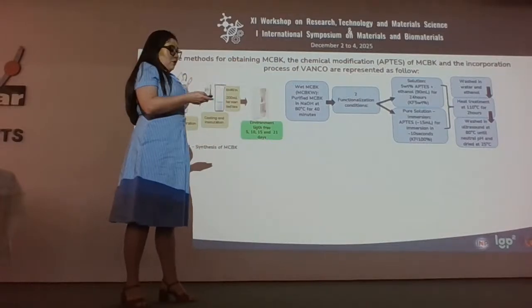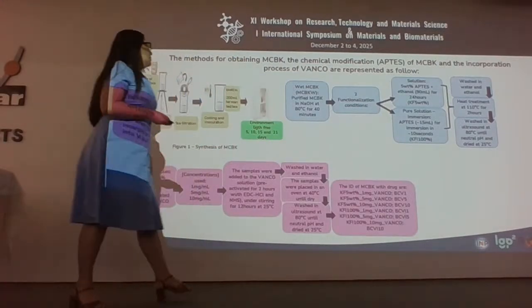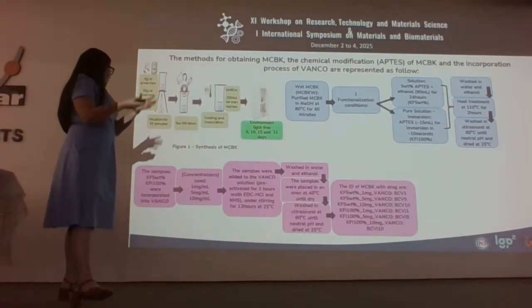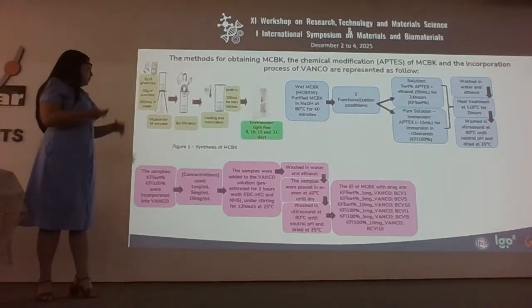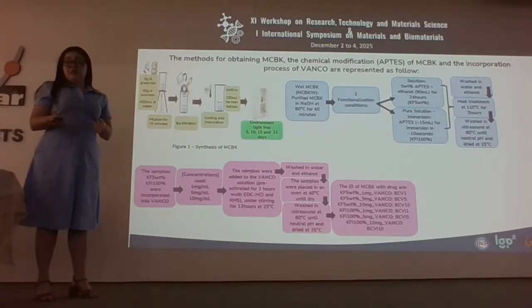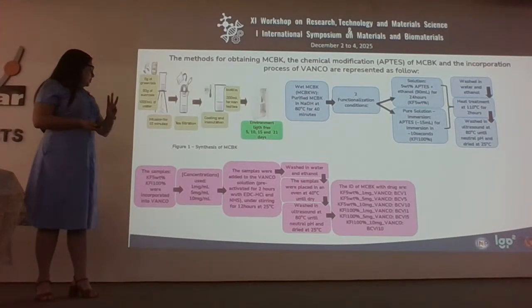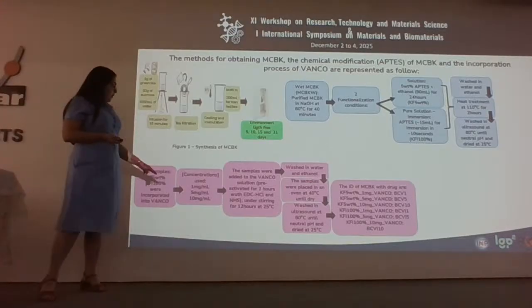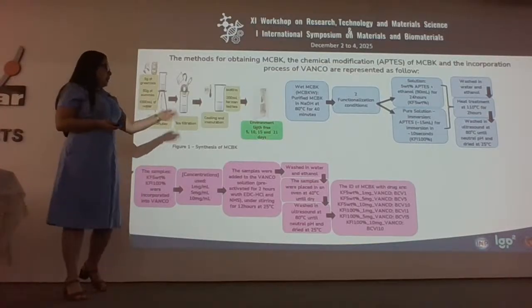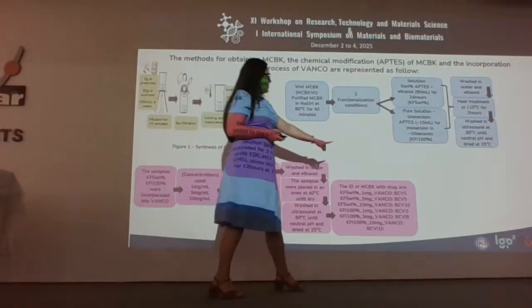And the steps follow for the functionalization part. And after the chemical modification, I use this part for incorporation of vancomycin. I use 3 different concentrations: 1, 5, and 10 milligrams. And here I use this abbreviation to identify the samples.